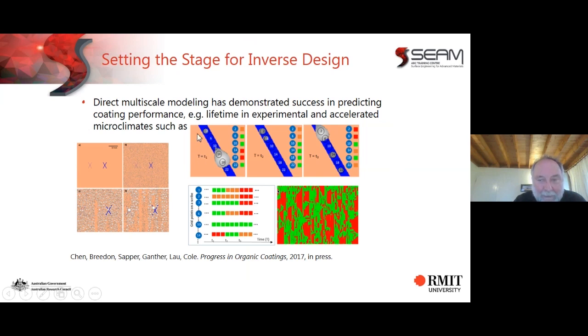So this is the paint film in this one of these little squares, and the little scribe is here in blue. And we could look at whether inhibitors can go from the paint film into the little moisture area, and where we can get inhibitor into the moist area, it's green. Where inhibitors can't reach the moist area, it's red. And so we can do a time and position map of when the inhibitor is protected or not.